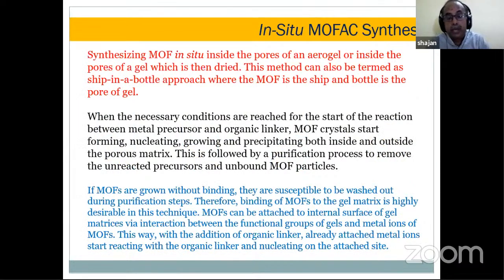Now here also you have to be very careful, because you are doing the process inside the aerogel itself, in the pores of the aerogel. One problem is that the MOF should be strongly bound to the aerogel structure. Otherwise, when you start washing in the final stage, you'll be doing several stages of washing to remove the unwanted, unreacted solvents. In such cases, if there is very loose binding, the MOF will go off along with the water. The second thing is, the MOF also will have some functional groups, and your gels will also have some functional groups, and these functional groups may make a link, because you are adding an organic linker. Instead of linking with the metal ion given in the pore, it may link with the aerogel, and some other compound will be formed. So these two things you should be very careful about when you are doing an in situ MOF synthesis.